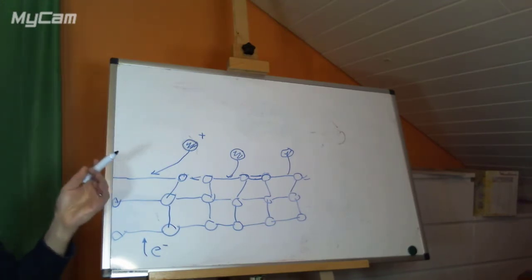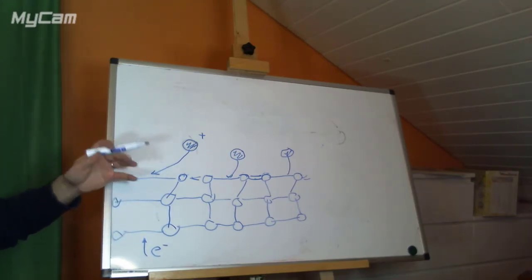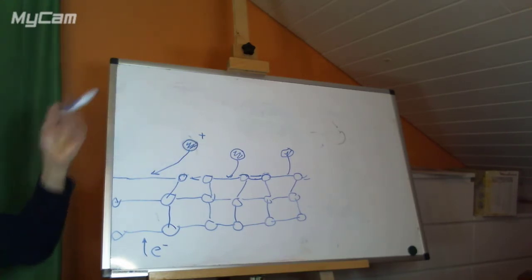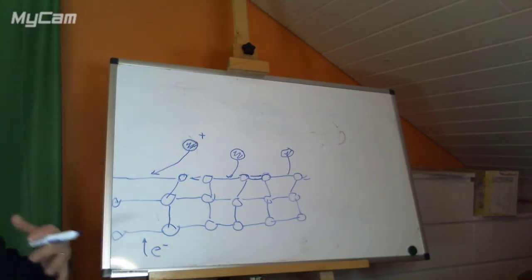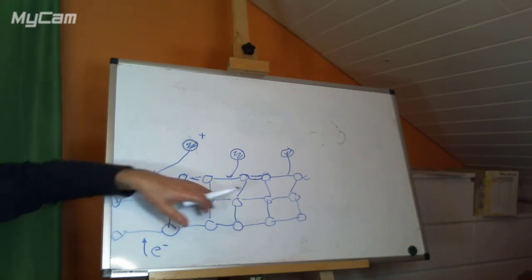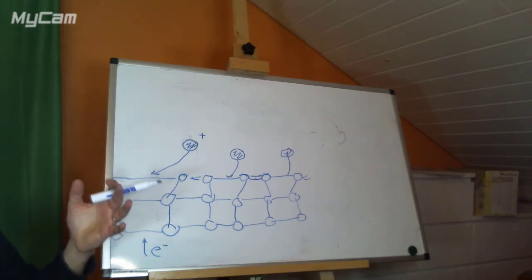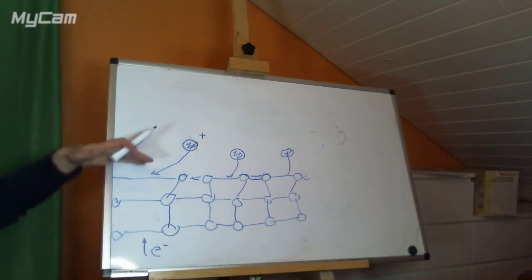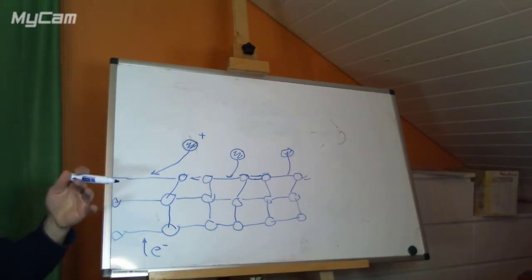But then we have to get back to the state that we had before, where we had this still strained, but it's strained in a different way to match the new crystal structure of our other material. So we're now going to have a relatively complicated procedure. First of all, we're going to put on a layer that is not like the second metal. It is mostly fitting the structure of our first metal. Then the second metal will try to make its normal crystal structure, which will completely distort it, and then it will make its normal crystal structure right up here. So we're going to end up with a gradual development of different things.